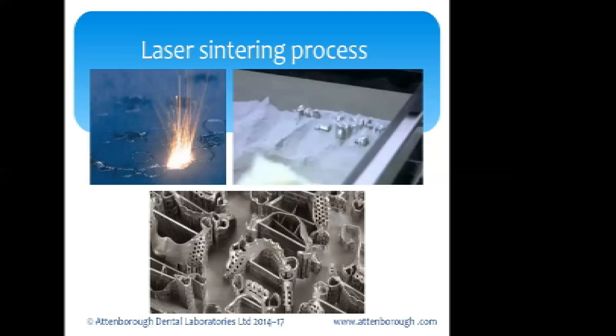And the way it works is that they have a powder bed, and a roller layers out a very thin layer of powder, and then a laser guided by the computer, a bit like the lasers at the supermarket checkout that are controlled by spinning mirrors, scans across the powder and fuses the powder together, and then another layer of powder is put down, and the laser fuses across it.